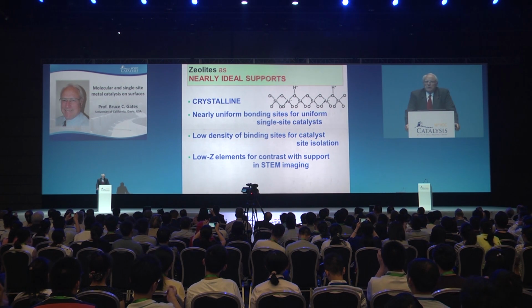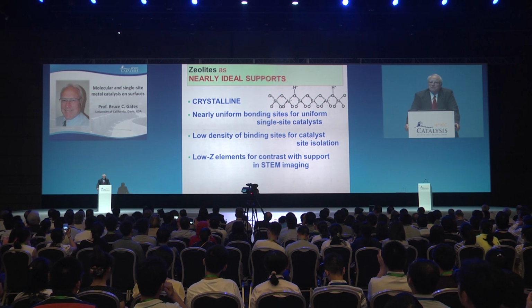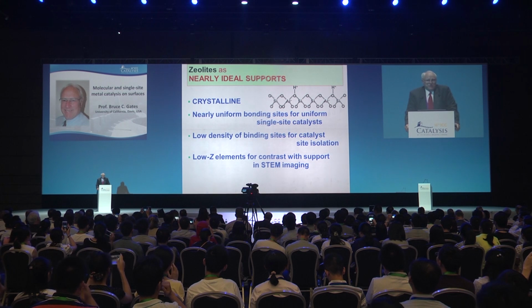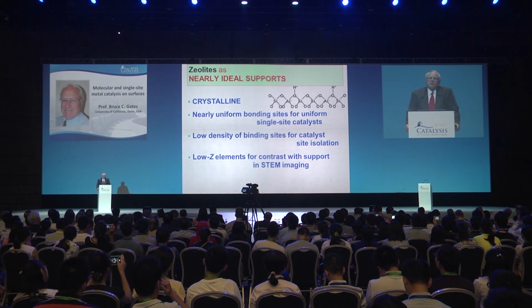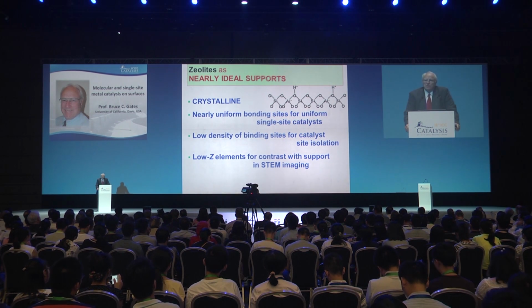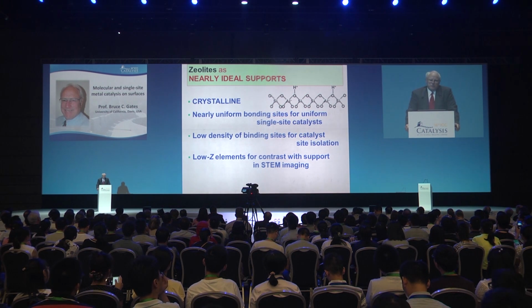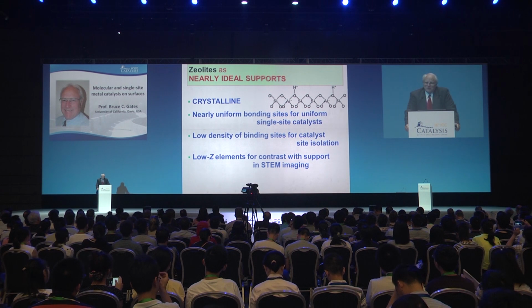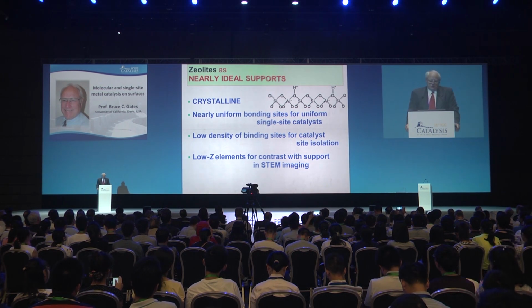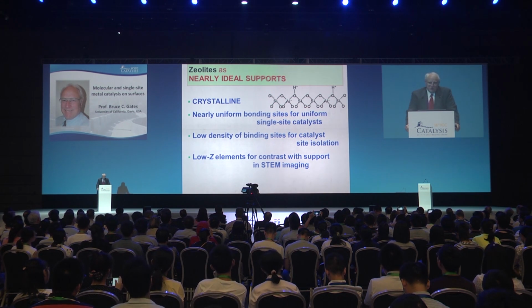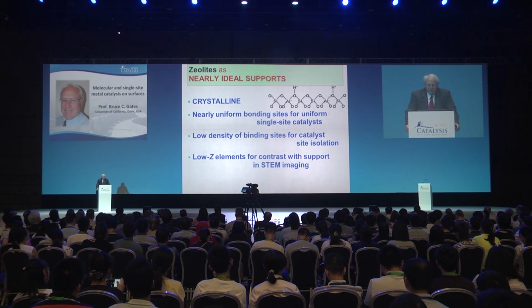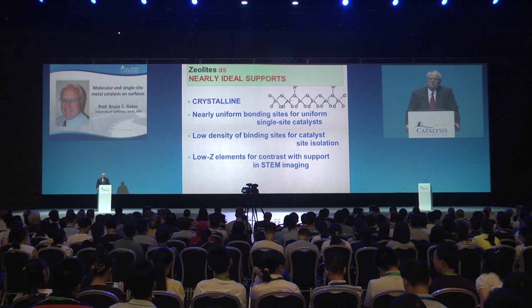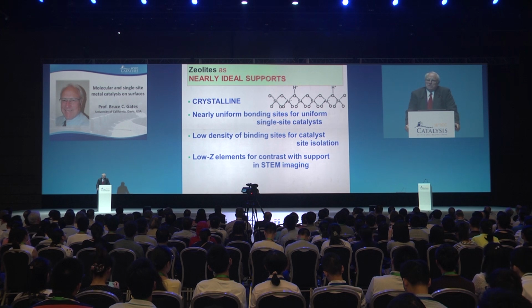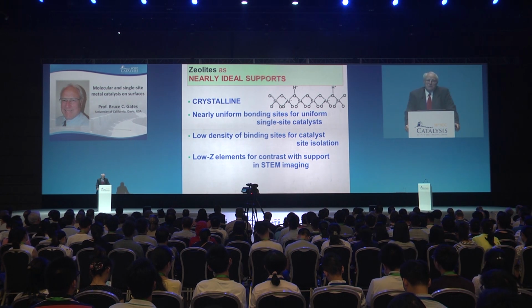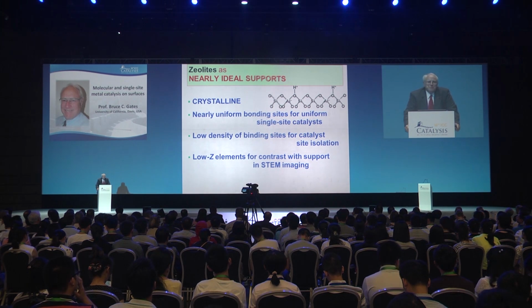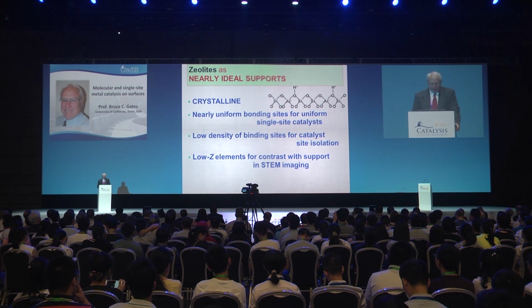For us, the prototypical support is a zeolite. Why? Well, it's crystalline—not perfectly, but often close—and it presents an array of reactive sites, proton donor sites that are strongly enough proton donating that they react with the precursors. Those sites can be tuned; we can make zeolites with high densities or low densities of those sites. If the material is nearly perfectly crystalline, it gives us a nearly uniform array of sites. Another important point is the atoms in this support have low atomic numbers, and for contrast with metals that have high atomic numbers, we optimize the opportunity to do atomic resolution electron microscopy.